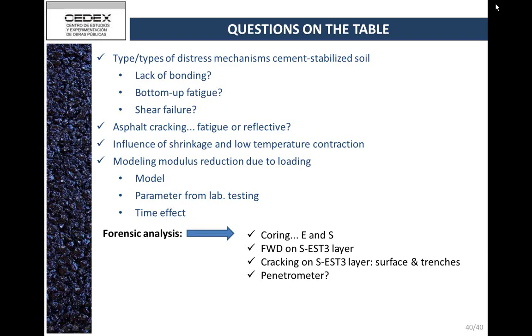Well, we use a small content of bitumen that has a very high penetration. It is a very soft bitumen, and we use like 1 pound per square inch. No, sorry, 1 pound per square yard. So, in fact, we did some testing in the laboratory just to make sure whether or not that bonding would be effective. And what we saw is that the bonding was really, really weak. It was not a matter of strength, but a matter of stiffness of the bonding.